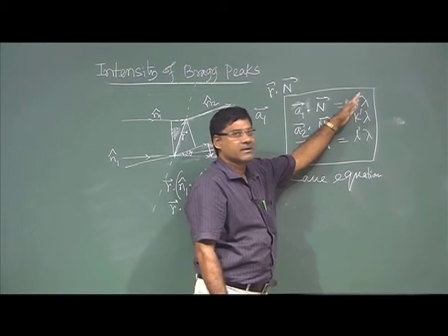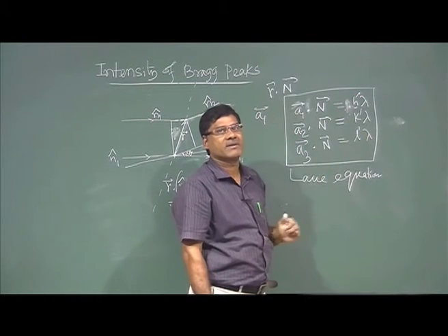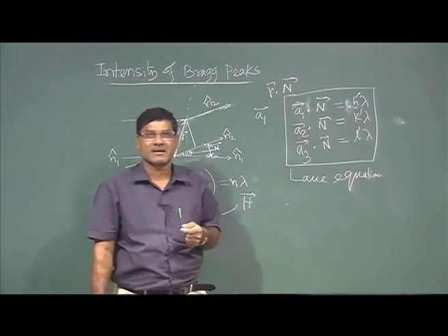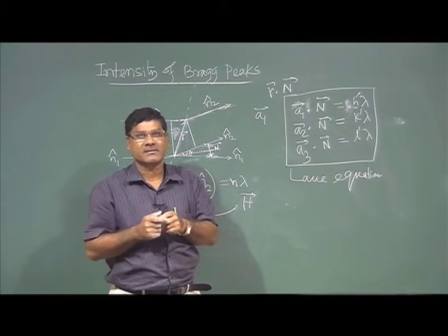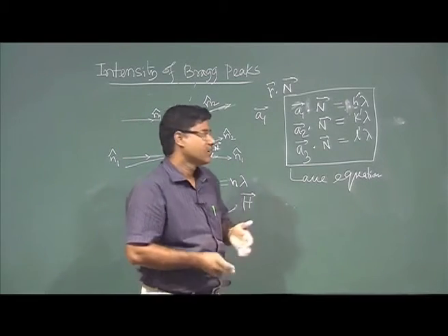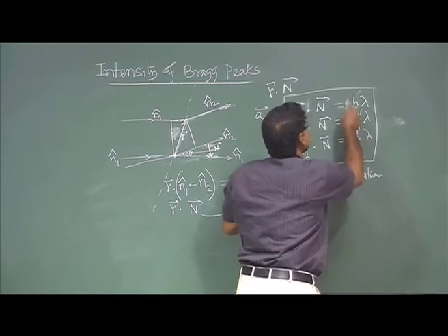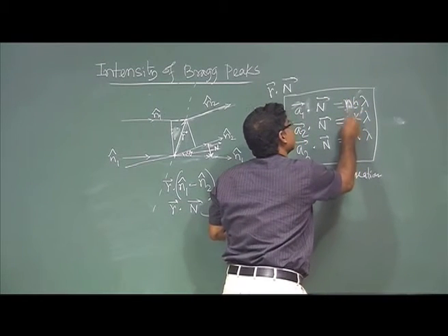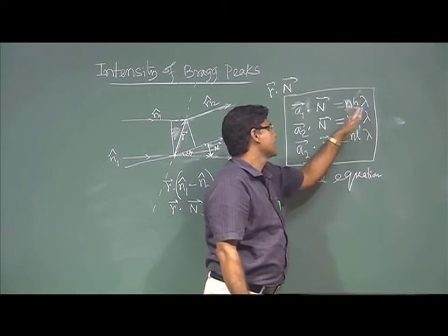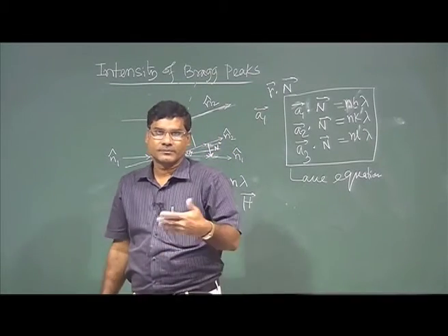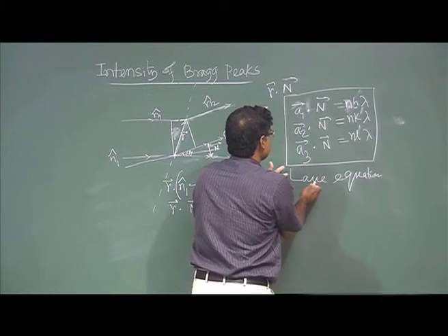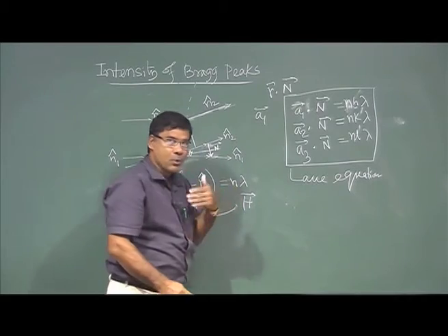Here, whatever HKL, I have written H dash, K dash, L dash. In the reciprocal lattice I mentioned that the common factor is important, whereas in Miller indices we remove the common factor. So, H dash I can write with the common factor as NH, NK, NL, right, and HKL is basically the Miller indices. Okay.